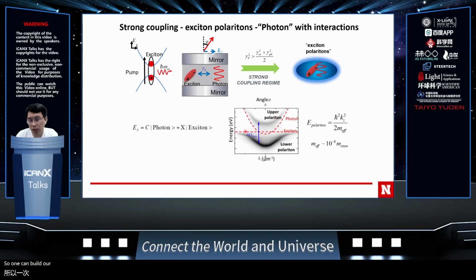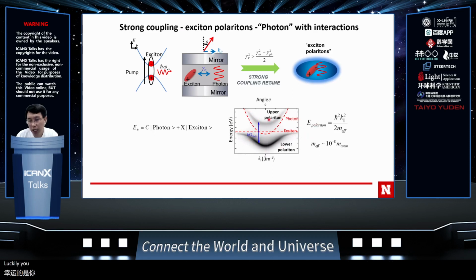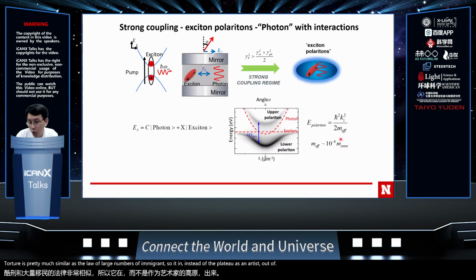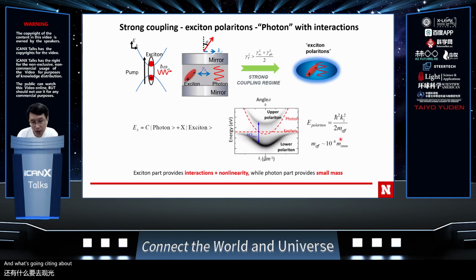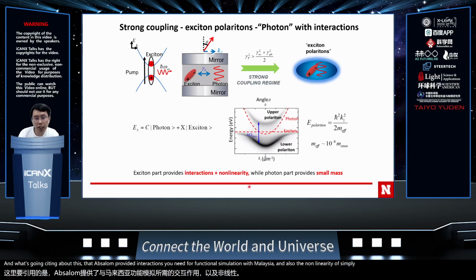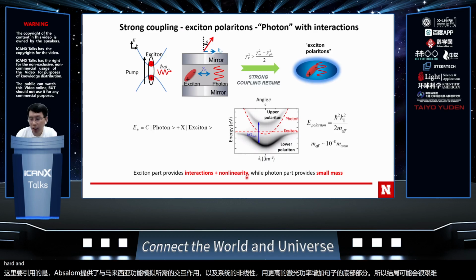So one can view that as a quantum superposition of photon states and exciton states, of the original exciton energy diagram and the cavity photon diagram. In the E-k diagram, they now become hybridized, form a Rabi splitting, and the new two states are called the upper polariton and the lower polariton. Luckily, you realize the cavity photon's dispersion curvature is pretty similar to the lower polariton's curvature. So the polariton has an ultra small effective mass compared with cold atoms, pretty similar to the cavity photon. And what's more exciting, the exciton part provides the interactions you need for quantum simulation or emulation, and also the nonlinearity. You can simply pump the system with a higher laser power and increase the boson particle density. So the N can be high and the effective mass can be really small in this system.